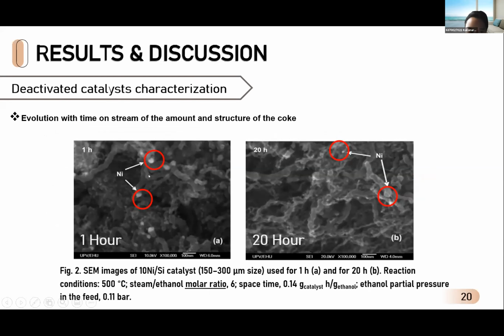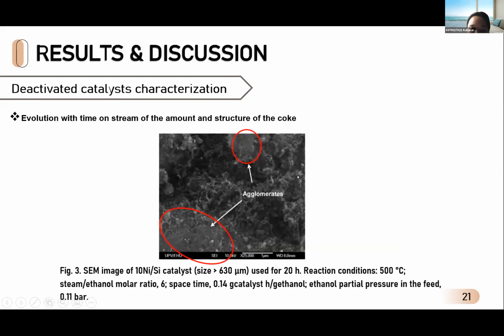In figure 2A, nickel particles are observed at the end of carbon filaments whose diameter is similar to that of the metal particle, which is consistent with the mechanism proposed for filamentous coke formation. In figure 2B, a high content of coke filaments is observed, with their size being highly heterogeneous, in the fractions of particles with size higher than 630 micrometers.